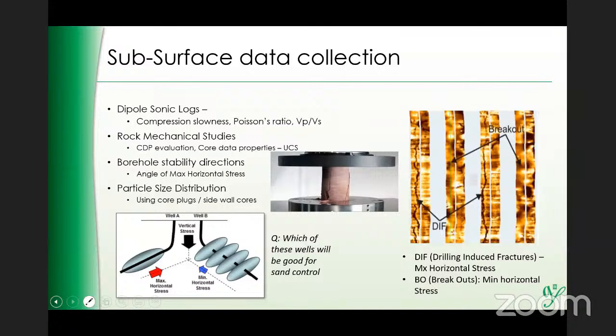So typically, as a thumb rule in the oil field, if your compressional transit time is less than 90, then we say the reservoir is very strong and does not need sand control. If it is between 90 microseconds per foot and 110, you say that it is in the transitional zone. And if your transit time is greater than 110 microseconds, then you say that it is a weak reservoir. Okay, so what we are looking at is both the compressional and the shear waves. VP and VS are the compressional and shear waves. You also look at a third type of wave.